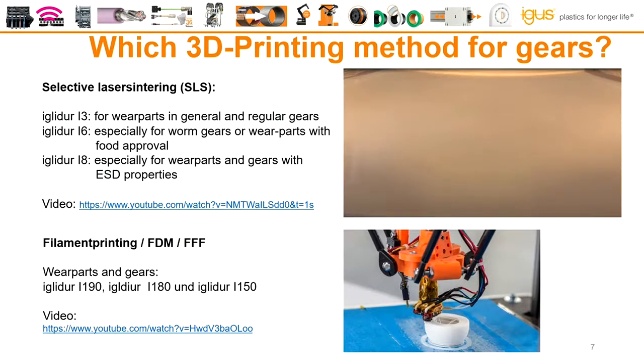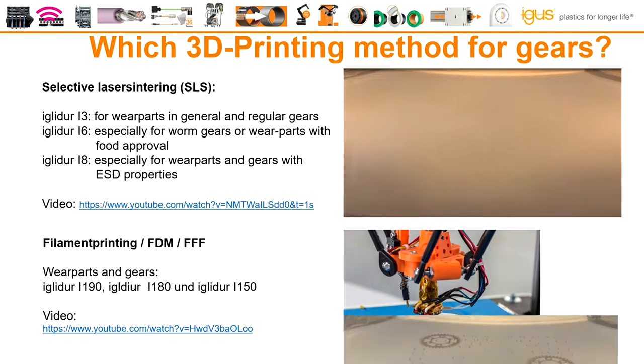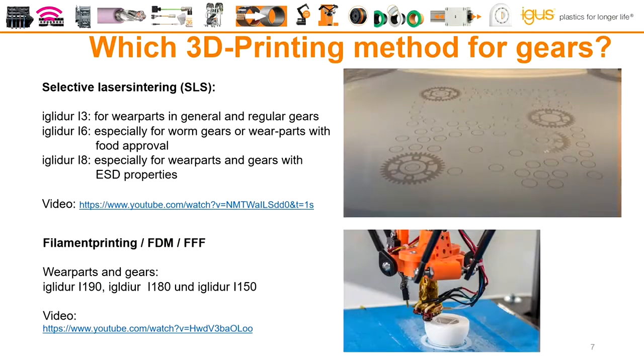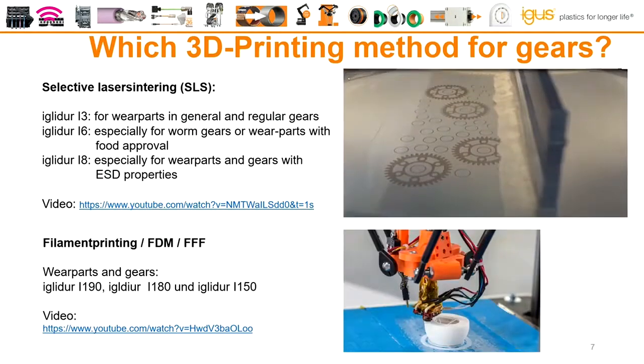The first one is laser sintering. Here we have a powder. You see it in the picture, and the powder is melted by a laser, layer by layer. The layer is 0.1 millimeter thick, and when the layer is lasered, then it moves down by 0.1 millimeters, and then the next layer of powder is spread out, and then the next layer is lasered again. And that's how we made by laser sintering about 120,000 wear parts in total, only here in Germany. And that's one method.